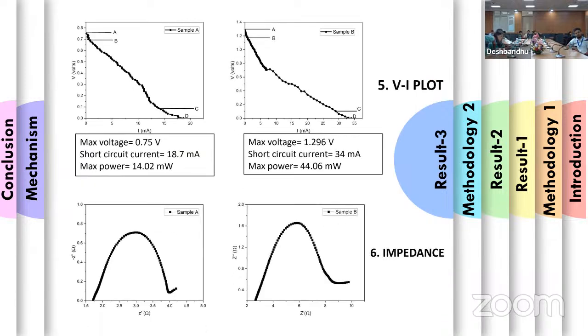Now, to test the hydroelectric cell performance, VI plot and impedance data were collected. From the VI plot, it was observed that sample A, which was treated hydrothermally at 95 degrees Celsius, displayed a short circuit current of 18.7 milliamperes with a maximum voltage of 0.75 volts. The sample hydrothermally treated at a higher temperature of 150 degrees Celsius showed a better short circuit current of 34 milliamperes and a maximum voltage of 1.296 volts.